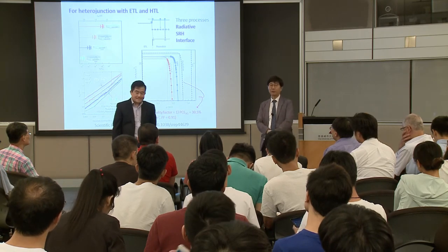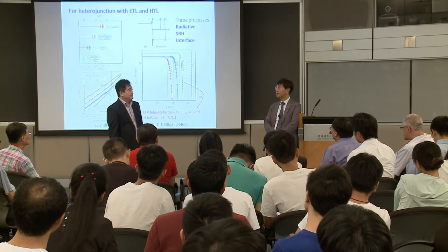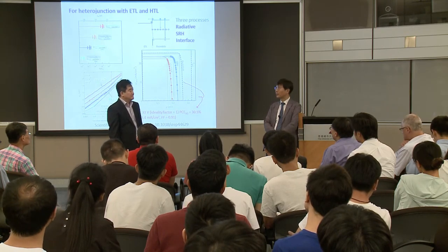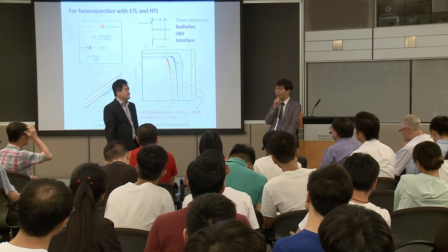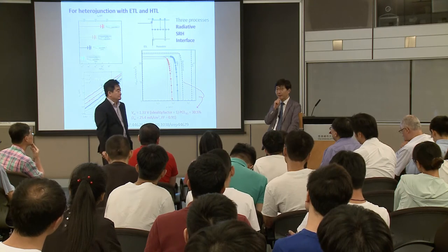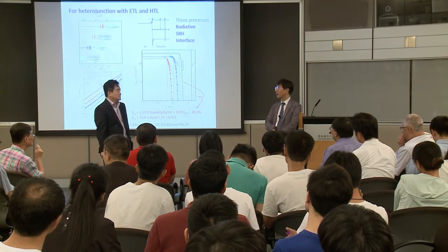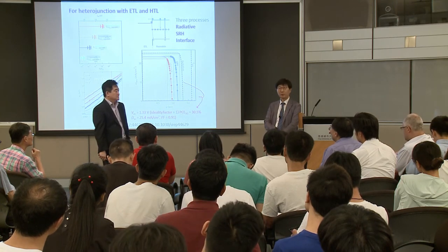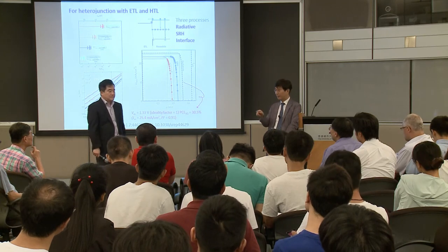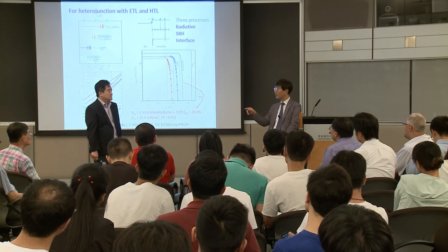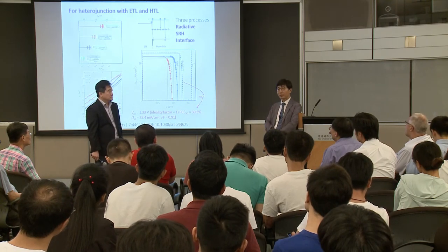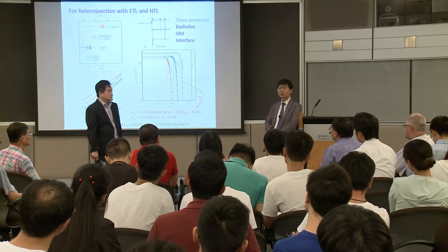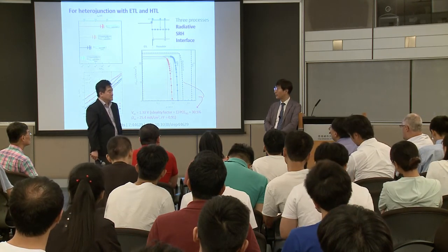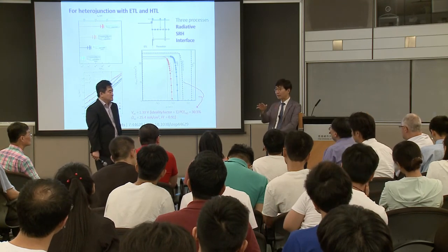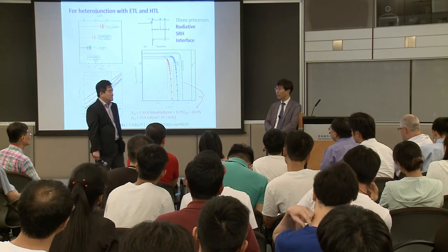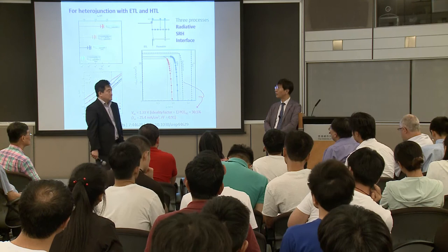But recently, we found, and I can definitely say, that 80-90% is reproducible. Yeah, we can get it. We also scanned the composition. There is no big difference between the compositions. But for instance, FA PbI3 85%, MA PbBr3 15%, this structure, if you make this structure quite well, then a lot of superlattice exists in the film. So high efficiency, low hysteresis contains fewer defects and also very low hysteresis.